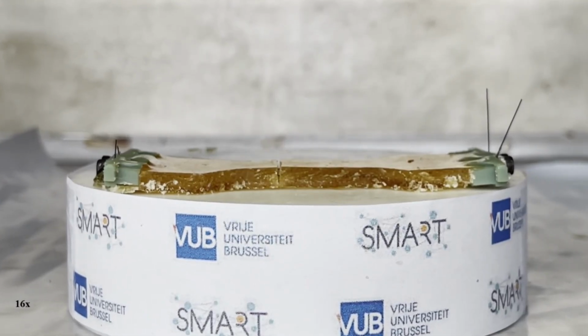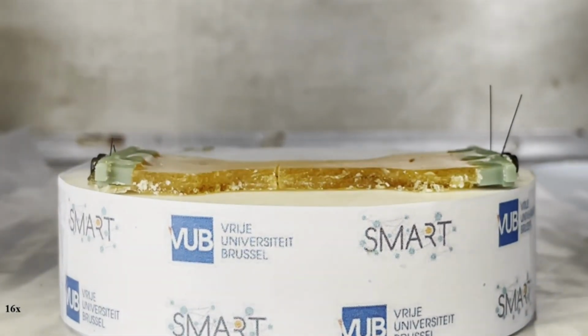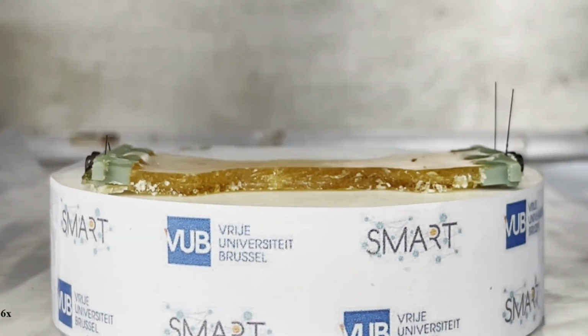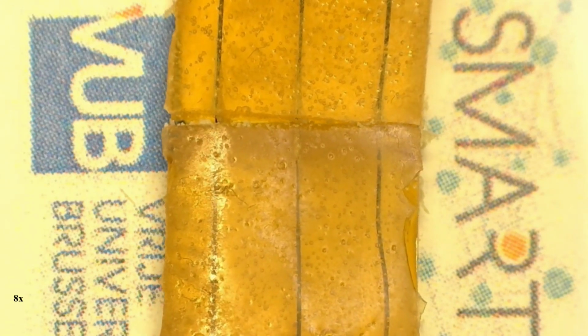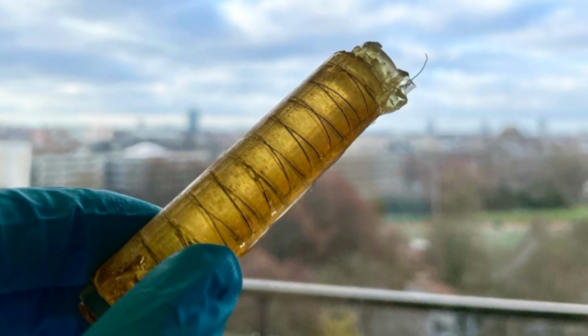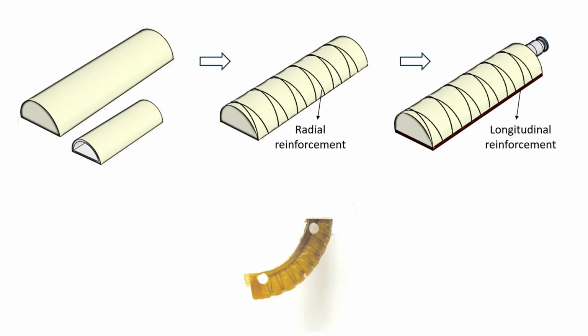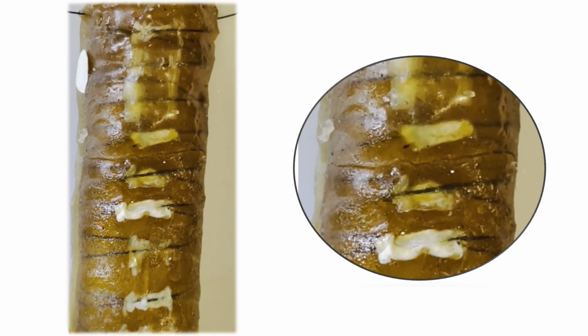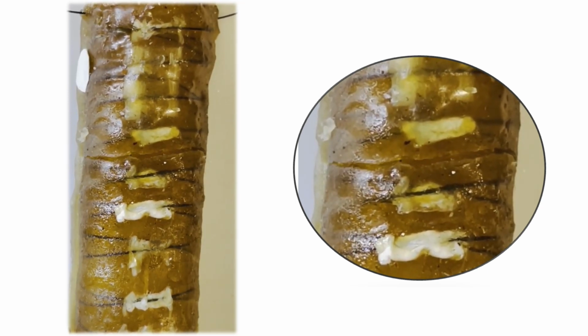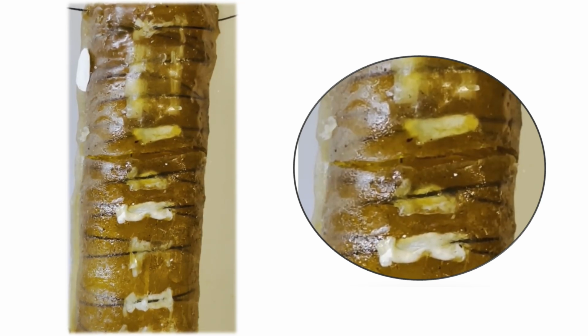After damage detection, one crucial phase of self-healing is closing the gap. As mentioned, self-healing materials cannot grow. As a result, upon damage, often a gap or incision is created that must be closed for self-healing to occur. To address this, I came up with the idea of using shape memory alloy wires, also known as muscle wires. When the temperature increases, these wires shorten in length, providing a mechanism to pull the damaged surfaces together. I integrated these wires into fiber-reinforced actuators, which are commonly used in soft robotics. These actuators are made by wrapping fibers, like nylon, around the soft chamber. So when the chamber is inflated, it bends, stretches, or twists. Instead of using standard fibers, I use shape memory alloy wires. While these wires are not self-healing themselves, they are highly damage resilient, making them ideal for this application.